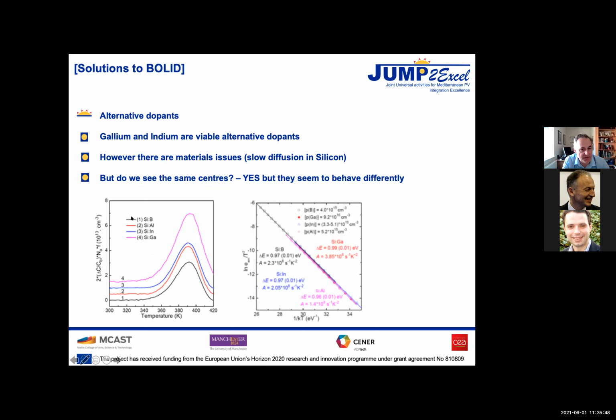What happens with gallium and indium? I've already said there are some problems with gallium and indium. They don't diffuse well in silicon. It's a different issue. But do we see the same signals? Yes, we do. So this is that high temperature peak for boron, aluminium, indium, and gallium. Aluminium is a dopant, but it's not practical for other reasons. But we see it for all those elements.